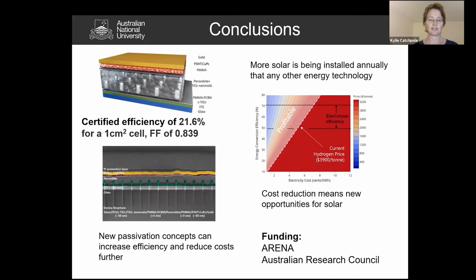We've reported a certified efficiency of 21.6% for a 1 square centimetre cell using this passivation approach with titanium dioxide nanorods. And this passivation approach is very general, actually. It's that balancing of passivation with charge extraction. So in this particular case, we've done it with titanium dioxide nanorods. As I showed, it's also possible to do that with combinations of passivation materials. So there's lots of different ways of doing it, but overall, it's a very effective strategy, especially for increasing the fill factor of these materials.